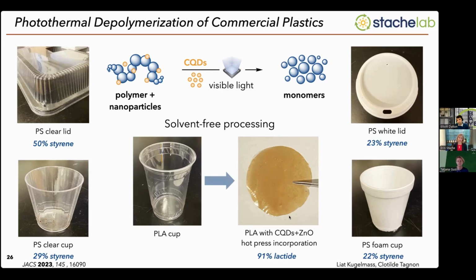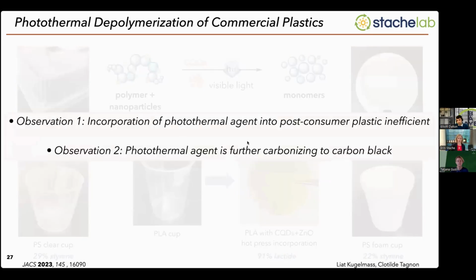So this was a great proof of concept. We identified a new photothermal agent that people hadn't been looking at before. We could depolymerize commercial polymers, including polystyrene. We had a few limitations here that we wanted to address. And so one was incorporating the photothermal agent into the post-consumer plastic, right? This is an extra processing step, which is going to increase the cost of recycling and hinder it being actually implemented at scale. And the second is that the photothermal agent was further carbonizing to something like carbon black. And so it wasn't stable, we wouldn't be able to reuse it, and people generally don't like materials to degrade or turn into something else as you're using them. You want to have thermally stable materials.